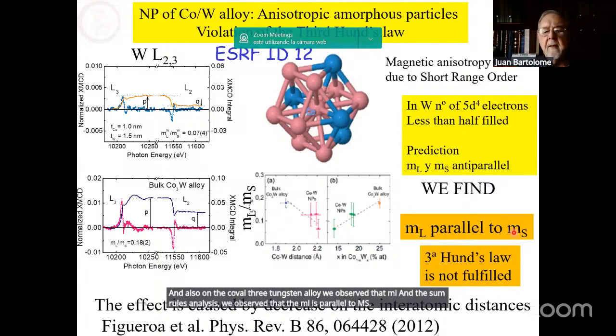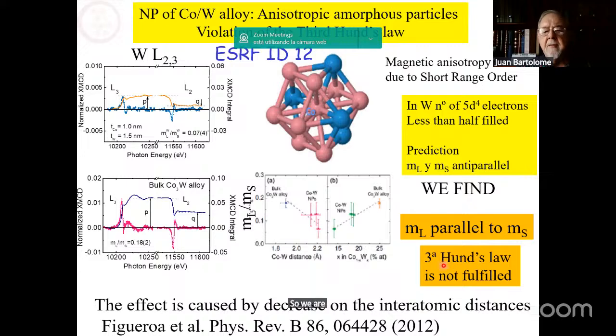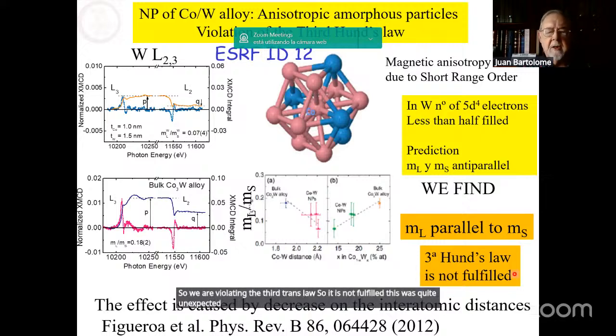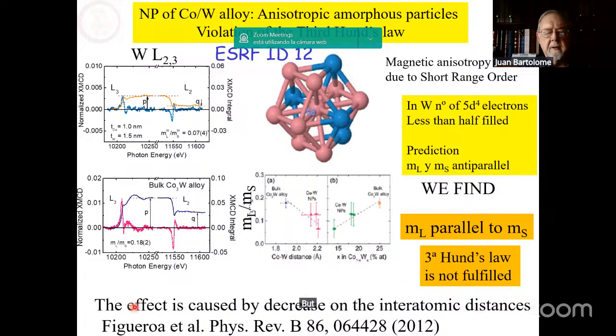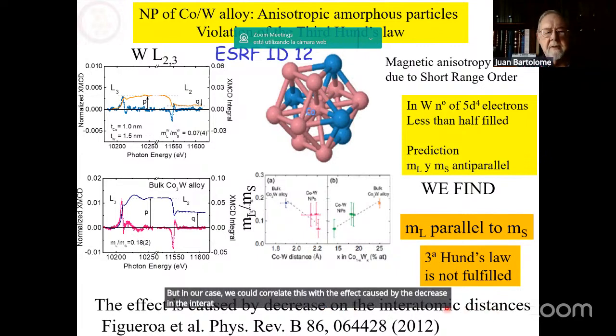So we are violating the third Hund's rule, so it is not fulfilled. This was quite unexpected, although it's not the only case in the literature. But in our case, we could correlate this with the effect caused by the decrease in the interatomic distances when cobalt is alloyed with tungsten.